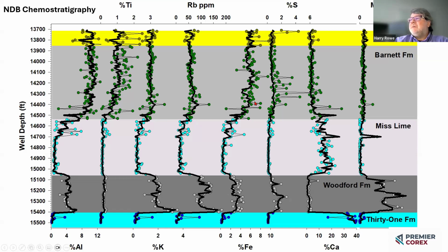What happens too, and look at sulfur here, this is a very pyrite-rich interval, and these pyrites are probably old cuttings. So some of that sulfide got oxidized, made it to the surface, and you have these sulfate crusts. That's right at the surface. The XRF makes it over quantify how much sulfur is there. Highly variable. Better to make a pellet.